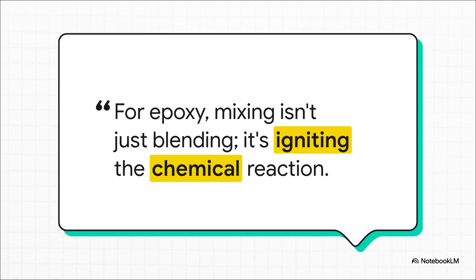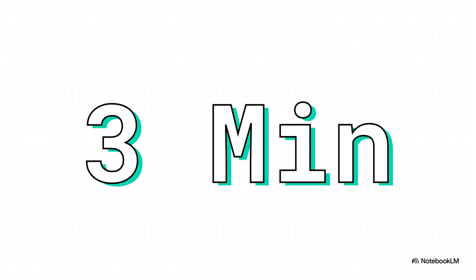The second you mix them, a timer starts, and mixing it properly is the only way you make sure that reaction happens completely and evenly. For the majority of epoxy systems, the absolute non-negotiable minimum mixing time is 3 minutes. That ensures that every single molecule of resin gets a chance to find and bond with a molecule of hardener. That's how you create that tough, cross-linked barrier you're paying for.